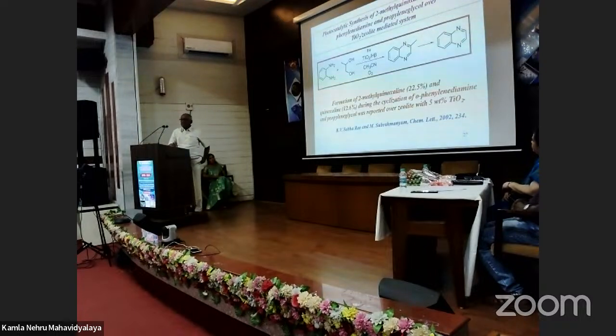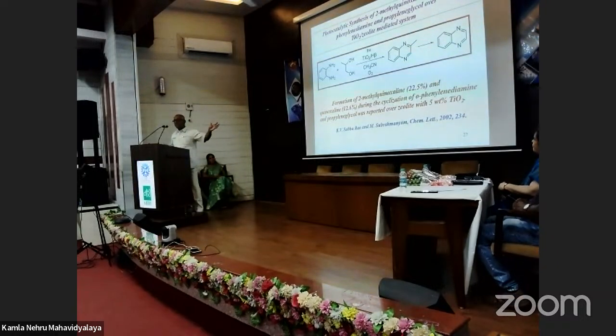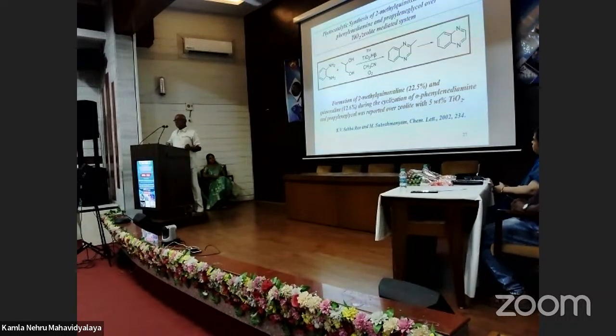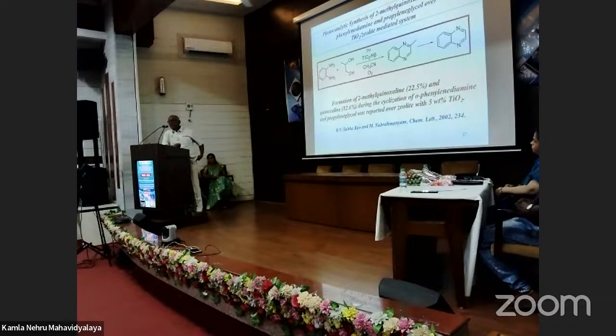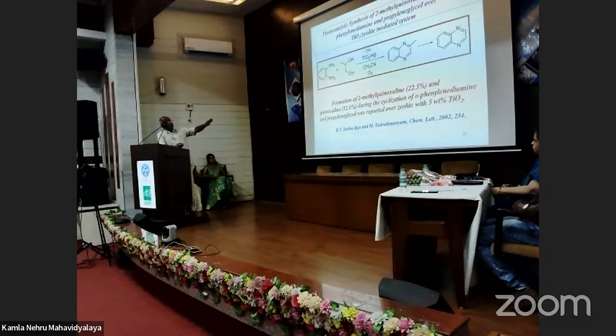And the first time we started our work on organic synthesis, this is the one which induced us, even inspired us, I can say. This is the work that my student saw in a paper, and he said, sir, they used TiO2 in acetonitrile, so why can't we use our silver TiO2 and other things? Then we used the same reactants, that is orthophenylenediamine and propylene glycol, and this was already reported by Professor Subbarao and Subramanian in Chemistry Letters, but the yield was very low, 22.5%, and only 12.5% of the 2-methylquinoxaline and quinoxaline.